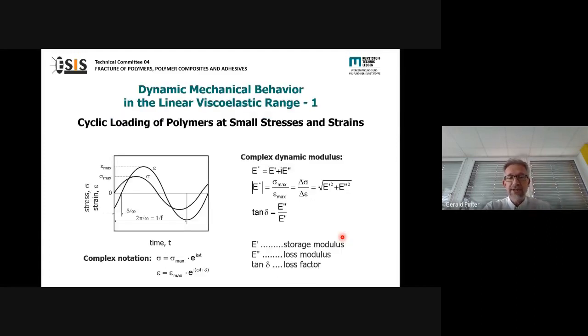I will go now directly into the situation of fatigue. When we talk about fatigue in polymers, we have to see that as a result of the viscoelastic behavior of polymers, if you load a polymer under stress control, for example, you typically have a shift in the reaction of the polymer. This time shift in the strains that we can measure is the reason that we have to deal with two moduli in the evaluation. We have the so-called storage modulus and the loss modulus. And tan delta is the loss factor, the relation between the loss modulus and the storage modulus. So it's a bit more complicated aspect we have to deal with in fatigue.